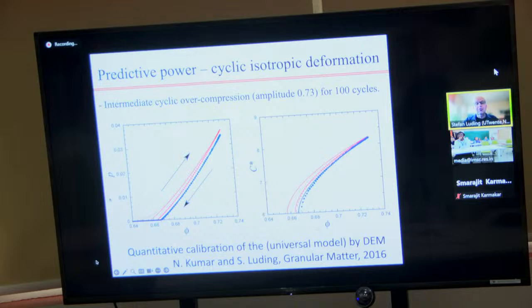Okay, so pressure and coordination number are results from the theory, those are the lines, and then I can compare them to DEM simulation. I showed this one already, and we did the quasi-static, TG equals 0, comparison already in 2016, but at that time we didn't have a theory which contains the transients, the non-elastic states, and the rate dependence.